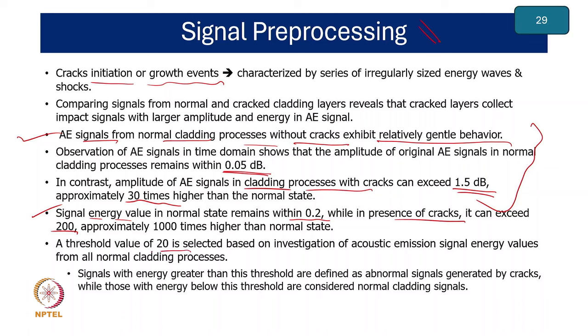That's why they kept a threshold value of 20 to investigate whether there is a crack or no crack. Lesser than 20, no crack; more than 20, crack. So this is the threshold that needs to be kept. That's why we say signals with energy greater than this threshold of 20 are defined as abnormal signals generating cracks, while those with lesser energy below this are considered normal cladding process.